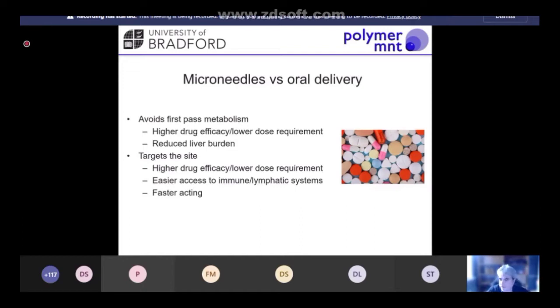So if you have a particular location in the body that needs a particular treatment, by applying the microneedle treatment in that area, you are once again targeting that site even more effectively. So once again, you get the same benefits of a higher efficacy and a lower dose requirement for that particular area. Another benefit as well is you get much easier access to the systems just under that top layer of skin. So it's much easier to get treatments to lymphatic systems because it's more readily absorbed at these sites rather than through oral delivery.